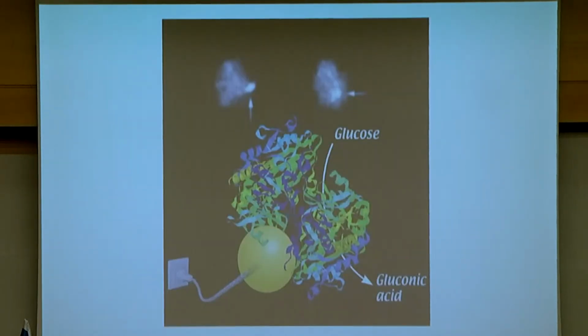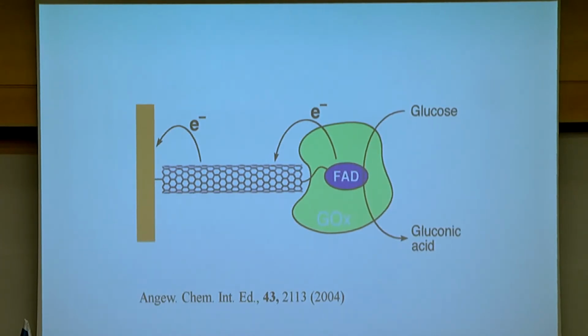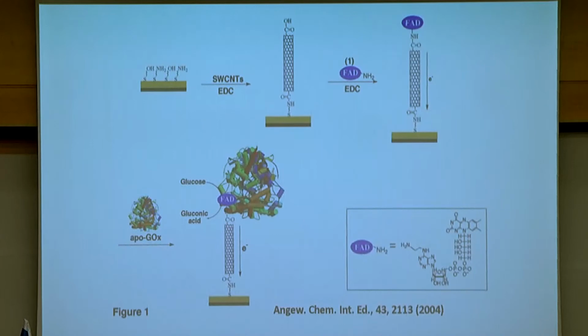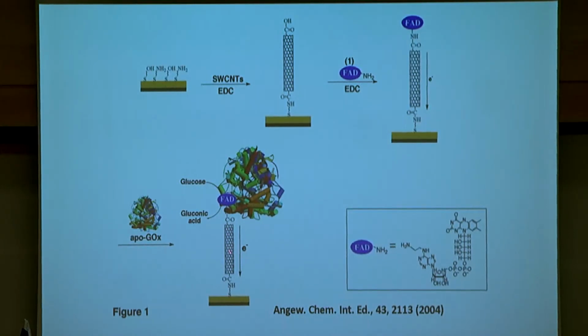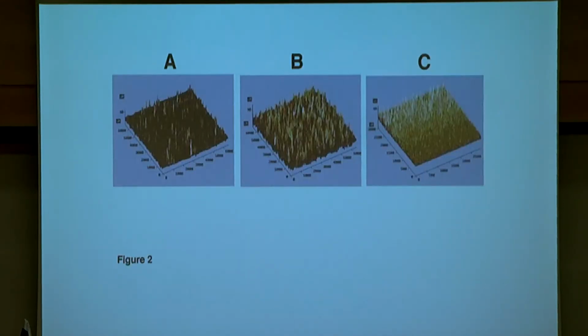Once we had this discovery of nanomaterials that can contact with an electrode, we moved on to carbon nanotubes, and we were able to contact the redox center of an enzyme by means of a carbon nanotube as a nanoconnector that connects the FAD center with the electrode. It was accomplished by assembly of carbon nanotubes on an electrode, modification of the head of the carbon nanotube with the semi-synthetic FAD cofactor, and reconstitution of the enzyme on the FAD cofactor. As a function of different carbon nanotube lengths, we were able to contact the enzyme with the electrode